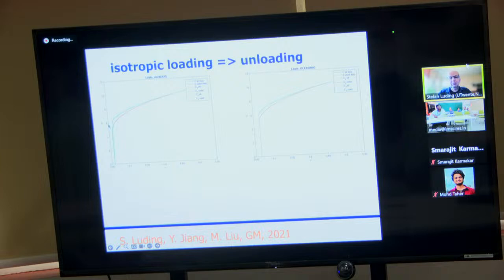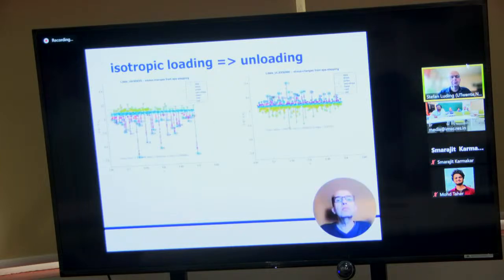Coordination number. And then we apply the same event analysis as we did for shear. For loading, we have a lot of stress drops, as you see on the left figure. And for unloading, we actually have stress rises because we go in the other direction. And the green dots in both plots also show the asymmetry of the probability distributions.